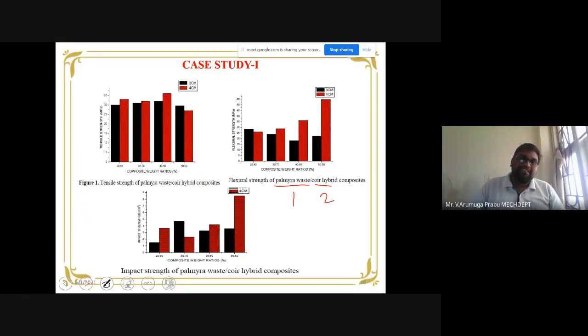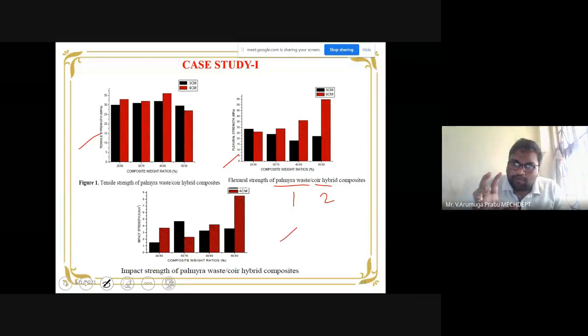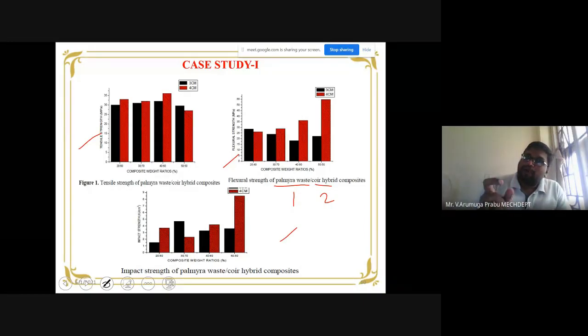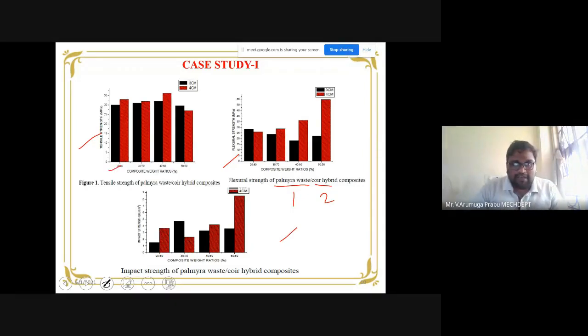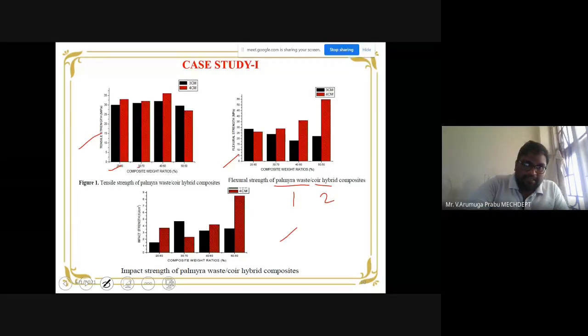So here also we note some interesting change in the mechanical properties, that is in the tensile strength, flexural strength, and the impact strength. First is the tensile strength. For these two wastes, another main thing that we have to notice when we go for preparing the advanced composite is the weight percentage of the reinforcement and the matrix, and the reinforcement length, all those things we have to consider. So here, if you note the graph, the first ratio is 20:80. That is 20% Palmyra waste, 80% coir. The next one is 30:70, next 40:60, and the last combination is 50:50.